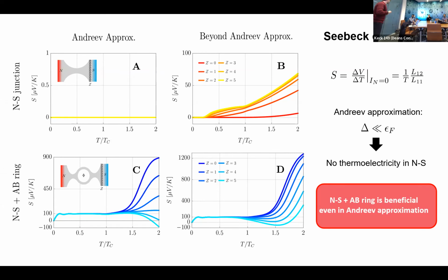So, just to remember correctly, the Andreev approximation would mean the region before which there is no normal reflection, right? The Andreev approximation means that you're linearizing your energy with respect to E over delta, so delta over E. So delta is very small, and you're linearizing. And what happens is that your wave number, the K there, is just the Fermi K. So if you do this, what you obtain is that the transmission function is always symmetric in energy, and indeed the Seebeck coefficient is always equal to 0, independently of the temperature and independently of the only other parameter, which is the transparency there.